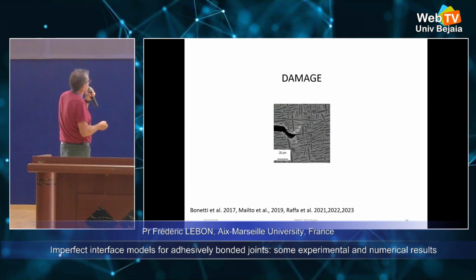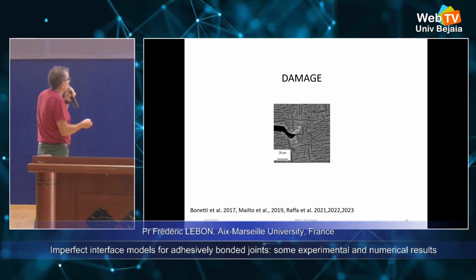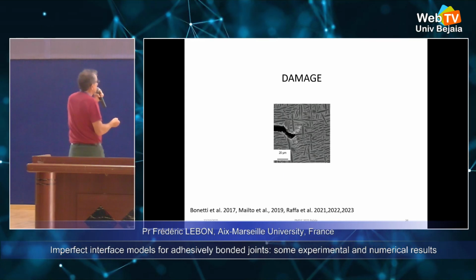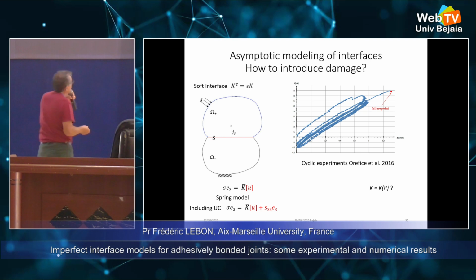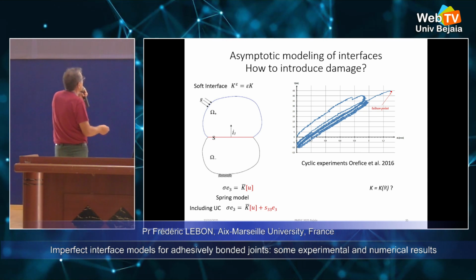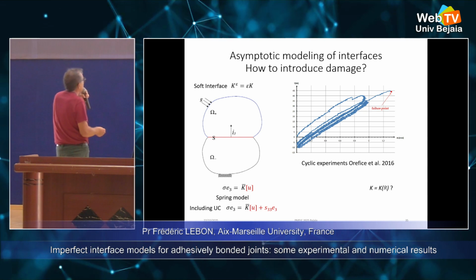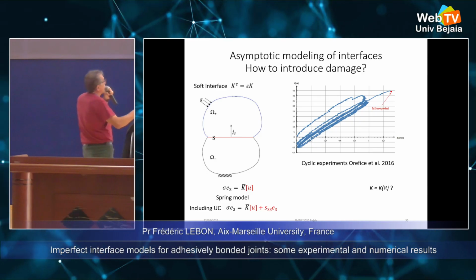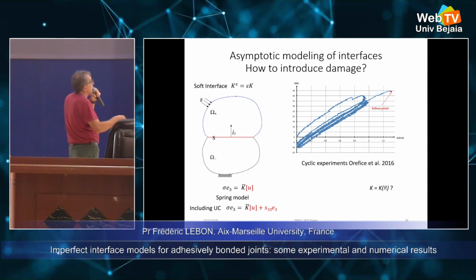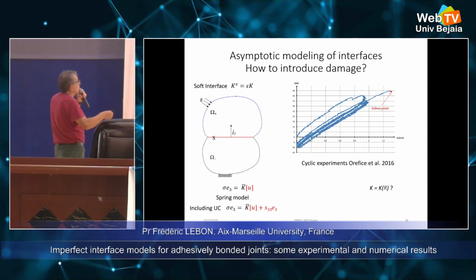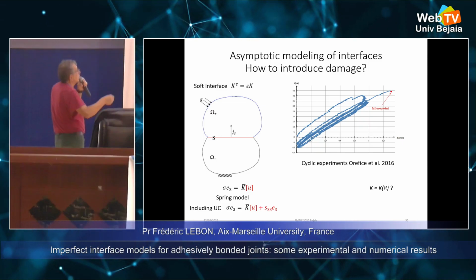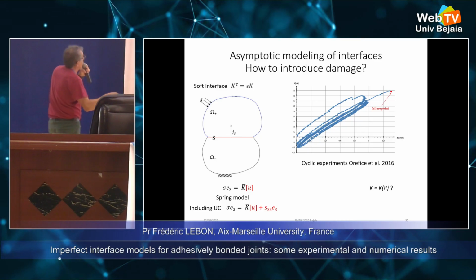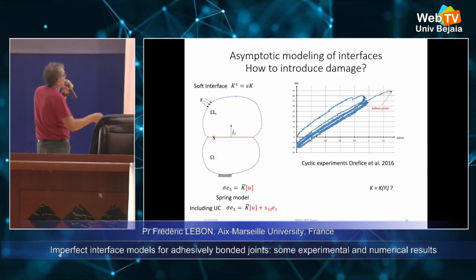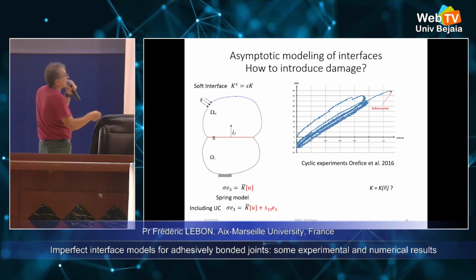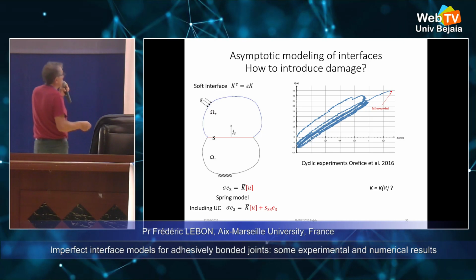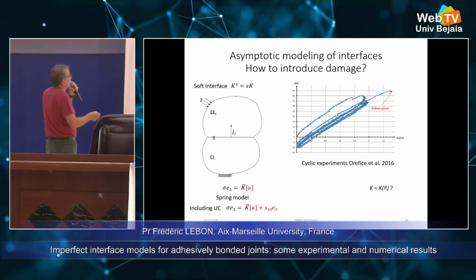So I show now how to introduce damage. A possibility to do that, because we have a spring model. It is a model like that. And if you proceed to some experiment, here you have a cyclic experiment. So loading, unloading, loading, unloading. At the end, we have the failure point. And we can observe that the line is not the same, in fact.